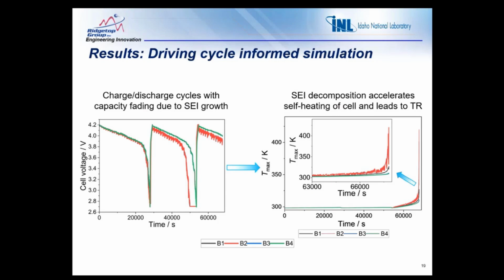We also see that the voltage profiles gradually decrease showing capacity fading, particularly in B2 compared to the other batteries. And also different cells experience varying levels of capacity fading, while B2 showing the most significant degradation. On the right, we observe the temperature behavior of the cells during the simulation. Gradual heating, initially all cells heat up gradually due to normal operation.